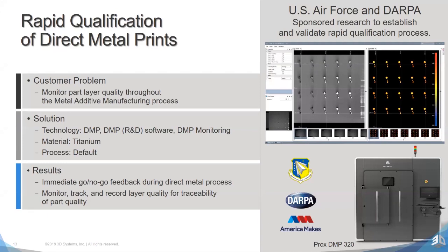Well, we just released DMP inspection that uses both of these technologies and is able to determine how well your part fused, and if there's any porosity inside. Our data has shown that we've been able to identify porosity at 100% for targets greater than 200 microns, compared to a CT scan. Below that, anything greater than 150 microns, we're still able to maintain 95% accuracy. And this continues to be improved. Even when you get down to small particles such as 50 microns, we're still able to identify the vast majority. This will allow you to have quicker validations and certificates for your metal printed parts.